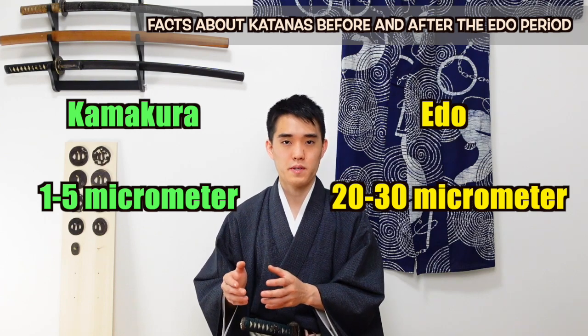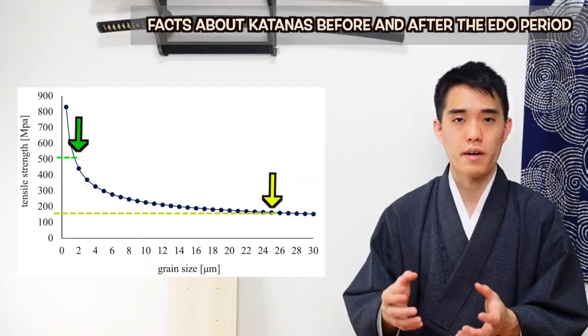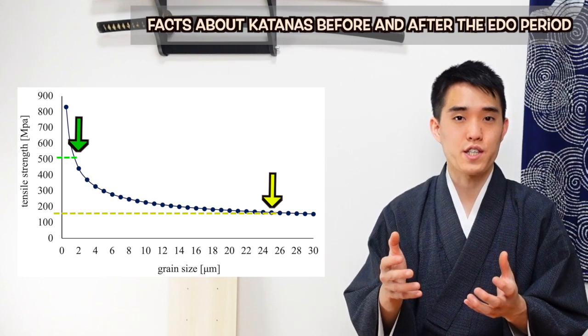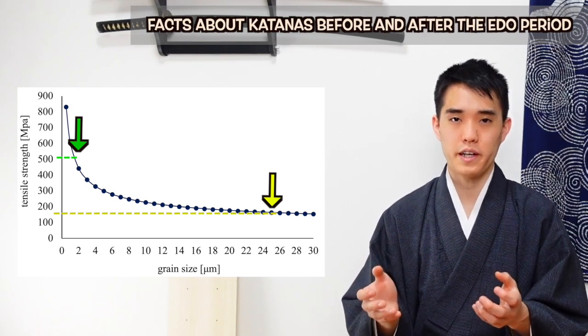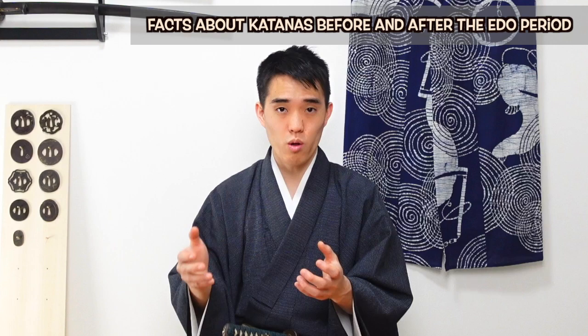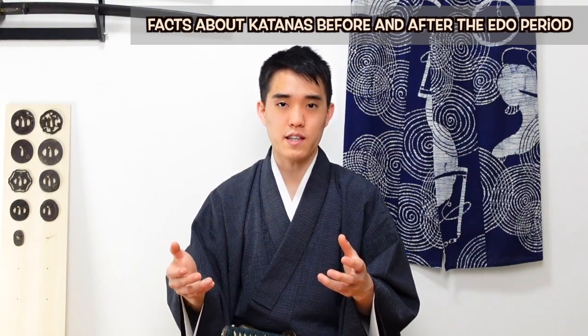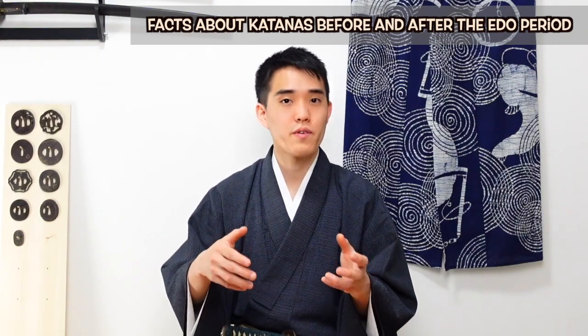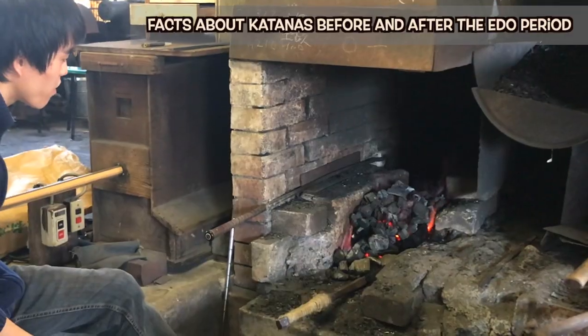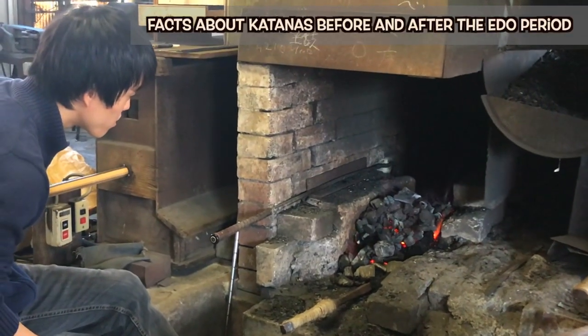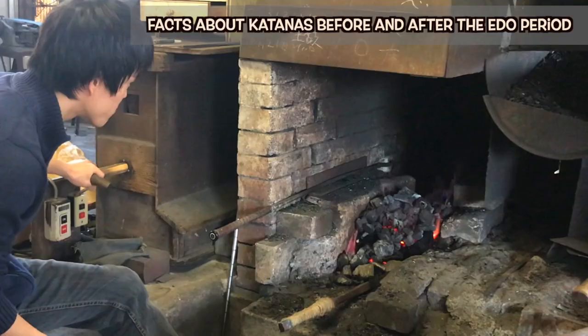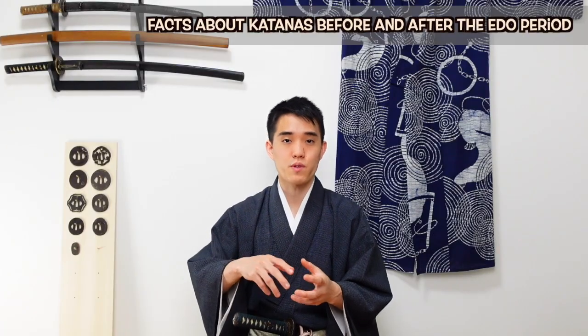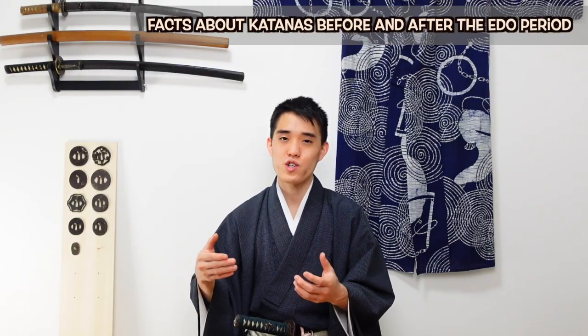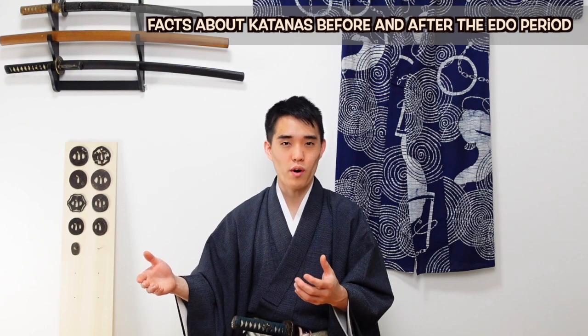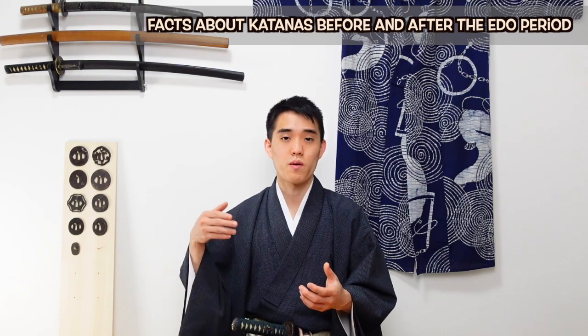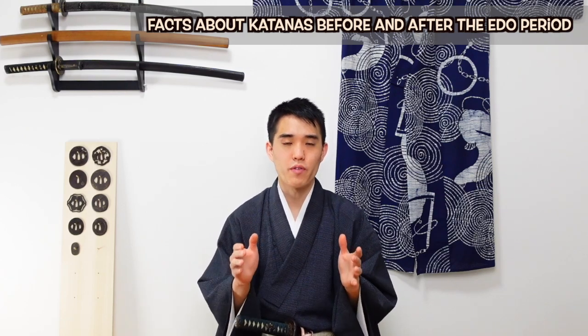That's a big difference. It means that the swords from the Kamakura period, which were analyzed in this study, are most likely harder, and when the crystal grains are smaller, this can lead to differences in texture and color, even if the material is the same. I think it is possible that sword making techniques, such as heating techniques, changed over time. Differences in the size of the crystal grains emerged, which could have contributed to spreading the rumors about superior swords from certain periods. But please note the following.